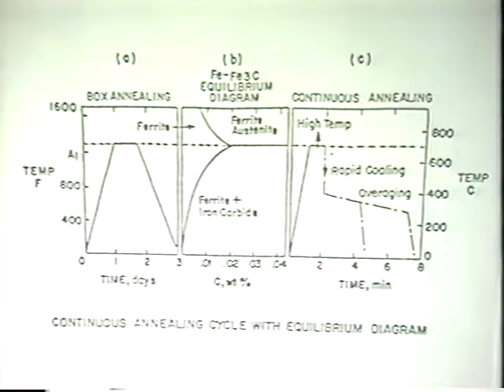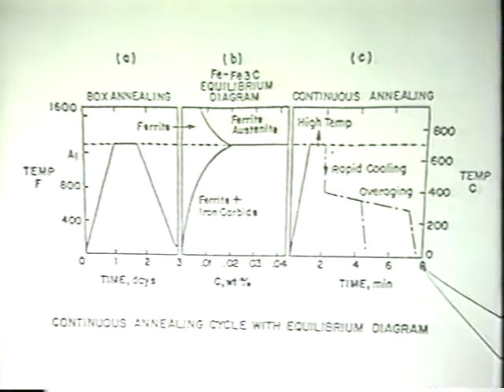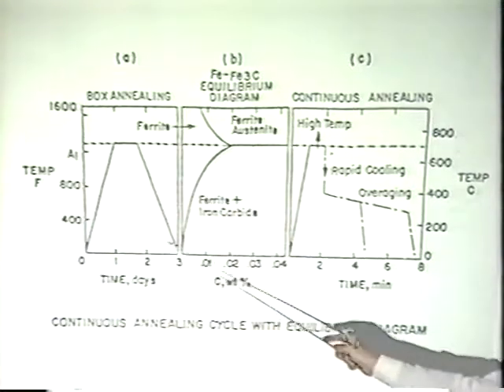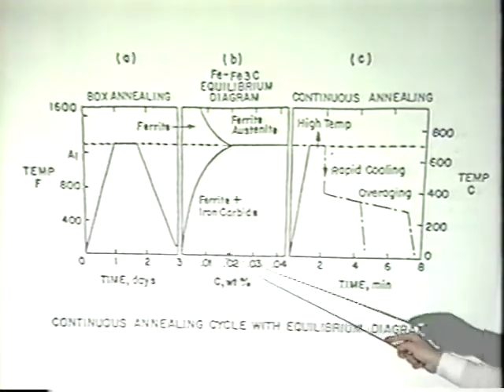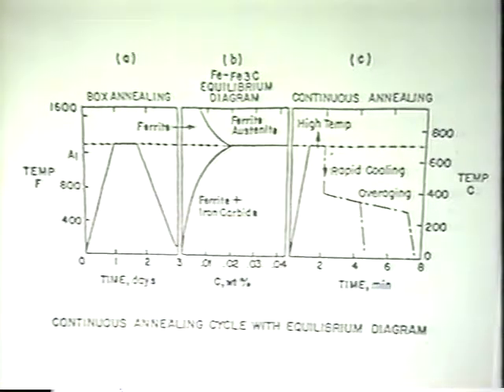Let's go back to the metallurgical chart I showed earlier that had grain size, residual stresses, ductility, and strength on it. Remember way over here on the right side of that graph, it said grain growth was the key to drawing quality products. You don't get grain growth in 8 minutes. Remember we said CQ just got us to recrystallization, and then you allow it to stay in there for a couple more days and you get grain growth. Big disadvantage with a continuous anneal process. Because it's so short, you don't have the ability to grow the grains.